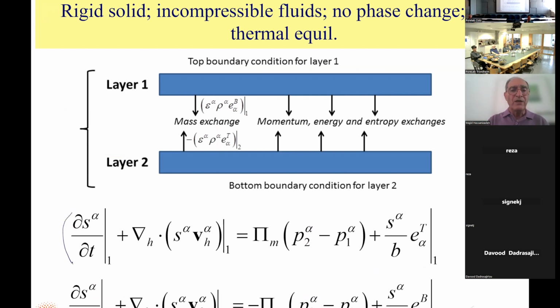So this means that we have one equation for, and that's the equation here, one equation for the top layer. In this case, this is the continuity equation. Change of saturation as a function of time is as a result of lateral fluxes. So the fluxes are lateral, but then there is exchange of mass between upper layer and lower layer. That's this one. As you can see, it's negative here. And then from the top, something comes into the upper layer, and at the bottom, something leaves the lower layer. So those are the governing equations.